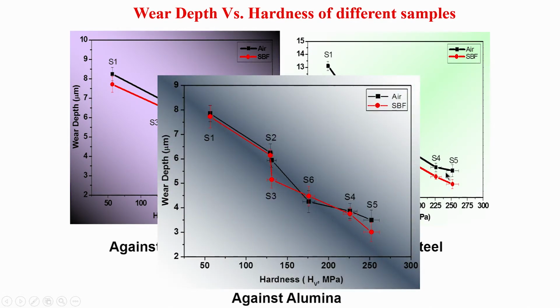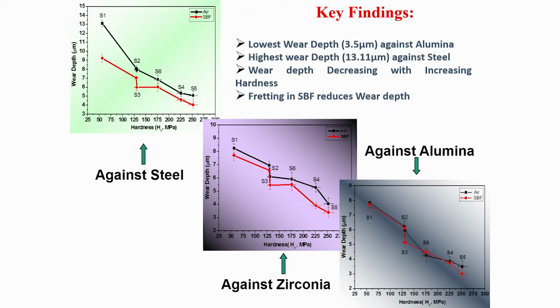And in case of alumina, as you have seen in the wear rate also, there is absolutely no statistically significant difference between the wear depth measured in the ambient environment and the wear depth measured in simulated body fluid after fretting testing.